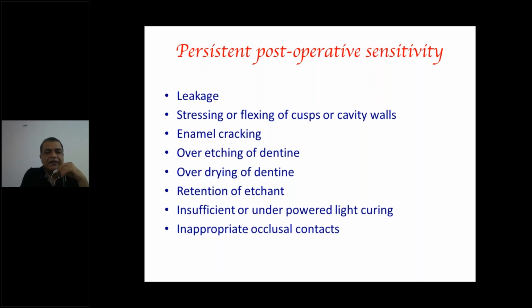Persistent post-operative sensitivity happens because of leakage, stressing or flexing of cusp, or enamel cracking. This is happening because you have not taken into account the polymerization shrinkage when you are working on the patient. If you follow the steps to reduce the polymerization shrinkage, you will not have this problem. That can also happen because of over etching of dentine or over drying of dentine, or maybe retention of etchant. But if you are using a newer generation single step self etch bonding agent, I think this problem will not be there. Please make sure that your light curing unit is checked regularly, and also check for inappropriate occlusal contact. If you take care of these points, the chances of post-operative sensitivity are negligible.